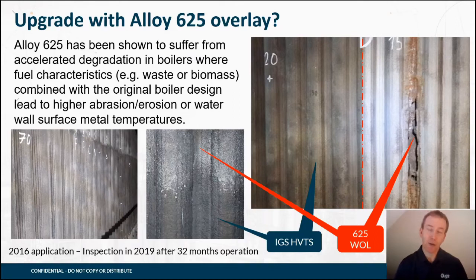When we think about an alloy upgrade in a waste to energy or a biomass boiler, we typically think about alloy 625 because that has been an industry standard in terms of surface protection in these types of units. However, it's not always applicable in all environments and is also not necessarily the most economical or viable option to install as a surface metallurgy upgrade. That can be when we're thinking about the time it takes to do the application. It can be the temperature resistance, if you see higher surface metal temperatures in the boiler. It can be with abrasion erosion, where the alloy 625 tends to suffer from more accelerated or faster metal loss from abrasion erosion. It can be to do with the fact that you don't want to put any heat stress into the boiler using a welding technique. It can be the weight factor if you don't want to install a 3mm thick layer and rather you'd look at a 0.5 millimeter layer of thermal spray. So there's lots of considerations to take into account.